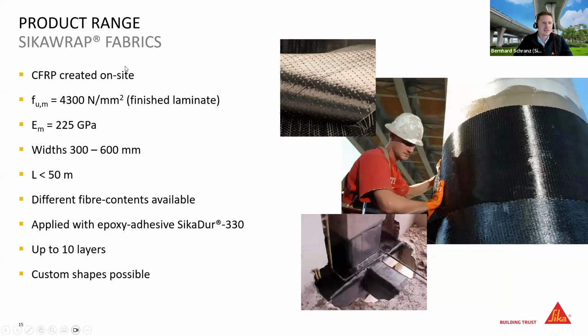Then next to the plates, we also of course have the fabrics, and the fabrics are usually CFRP. The reinforced polymer is created on site. That means you take the fibers as a sheet, and then you apply them together with epoxy onto the structure, and then the CFRP is created. Material parameters are a little bit different, also the stiffness; you will find all this info in the data sheet. And usually we have widths of 300 to 600 millimeters, and these are usually the roll lengths.